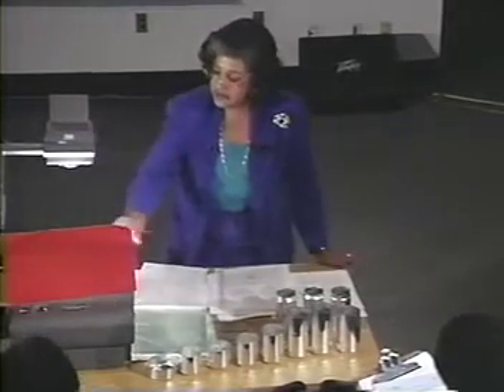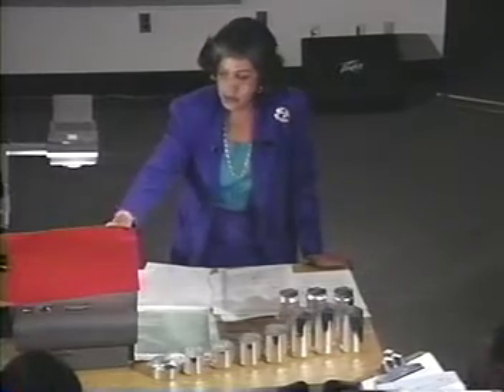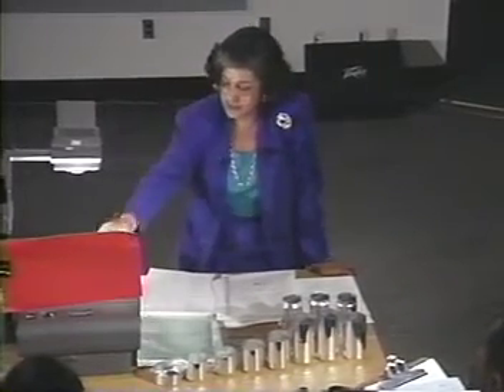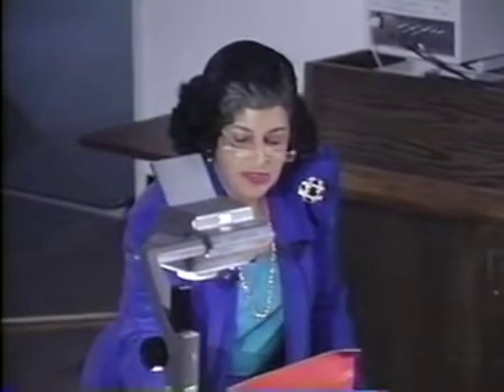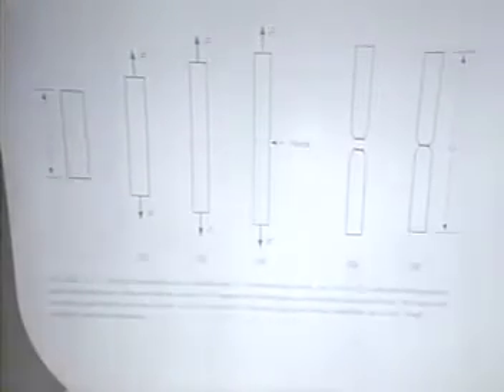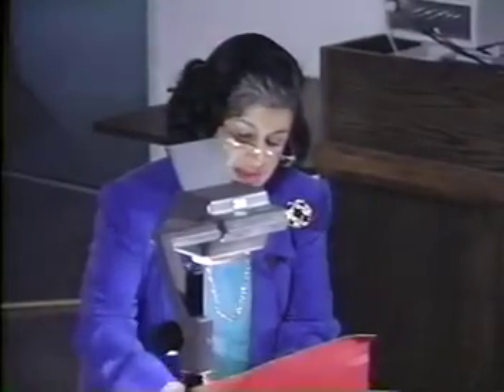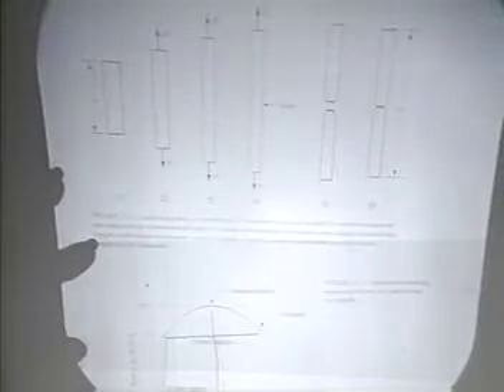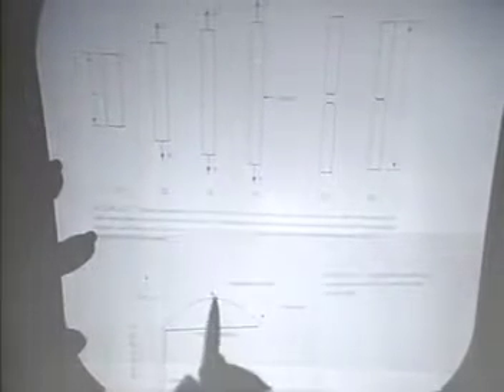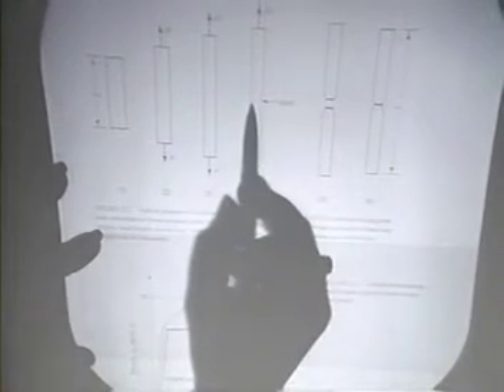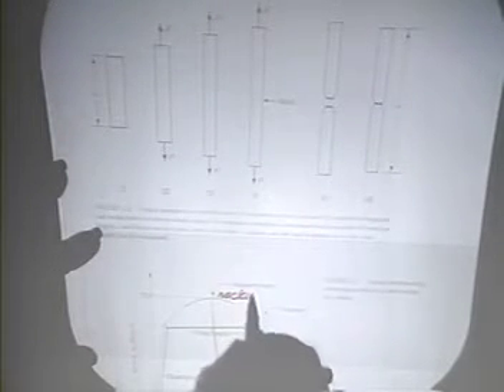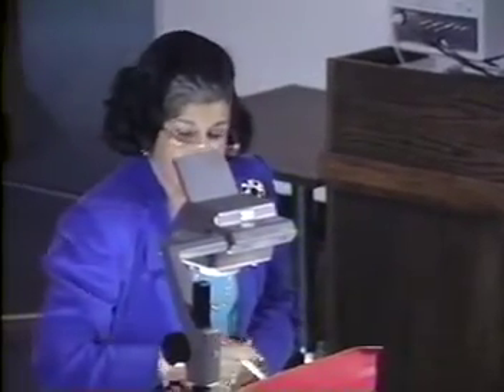Okay? Now, referring to the tensile specimen that generated the stress strain curve, it looks just like a flat bar or a round section of this could be a cylindrical section on a circular tensile bar. This is your gauge length. When we look at the stress strain curve here, during the elastic part, the bar is stretching uniformly along its length. Okay? Once we reach the maximum load here, it tends to deform more in a local area than along the whole length. That we call necking. So this is where necking starts, at the top of this curve. And the cross-section then becomes smaller at a much more rapid pace and a lot longer and eventually breaks off. Okay?